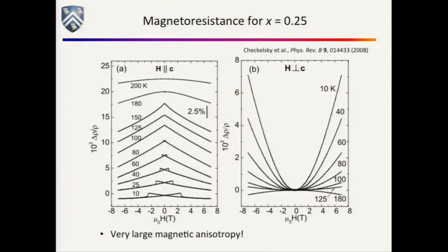And if you do the magnetic field in the plane, again, you see on the order of a couple of percent, a few percent, and the shape looks quite different. The fact that these things look very different is, again, a signature of the anisotropy. So if that was the whole story, then I would stop here and go on to the next topic. But that's not the whole story.